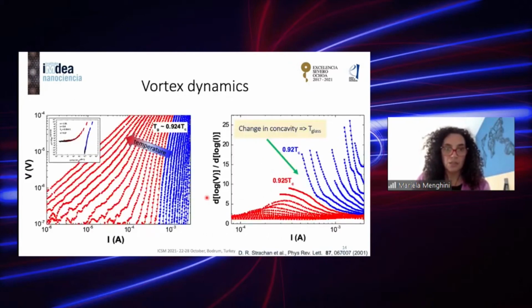These are the examples for the first and the third matching field, where we see this consistently for different fields. The other thing that we looked into from the IV curves is that the IV response also gives information on the vortex structures. As you know, what we did here is to take the derivative of the IV curves as a function of current, and then we see that at higher temperatures there is a divergence of this derivative, while at lower temperatures there is this maximum that moves with current.